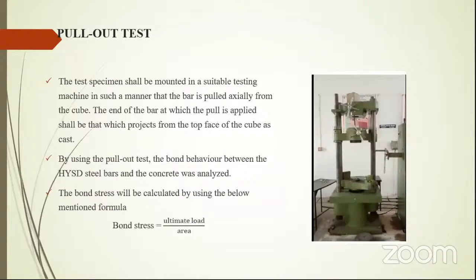Pull-out test. The test specimen shall be mounted in a suitable testing machine in such a manner that the bar is pulled axially from the cube. The end of the bar at which the pull is applied shall be that which projects from the top face of the cube as cast. By using the pull-out test, the bond behavior between HYSD steel bars and concrete was analyzed.